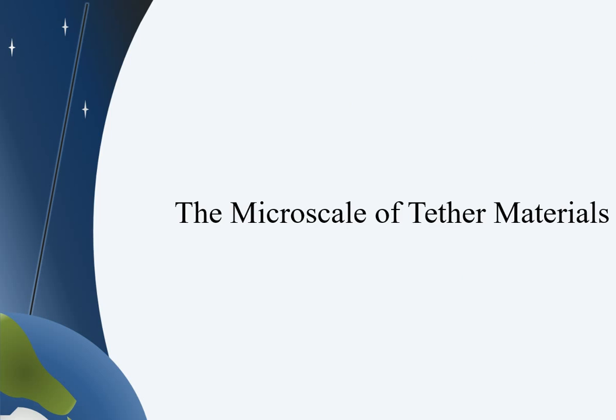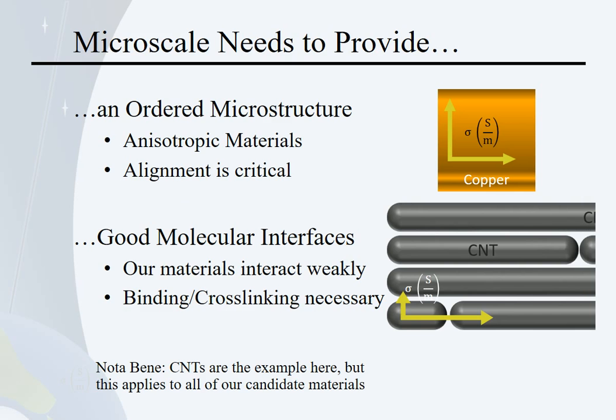So let's talk a bit more about that microscale structure. Now we need an ordered microstructure because both carbon nanotubes and boron nitride, and to a lesser extent graphene, are all anisotropic materials. Now we're used to isotropic materials. Let's use conductivity as an example. Copper is isotropic. If I have a cube of copper and measure from the left face to the right face, its conductivity, it will have a certain value.